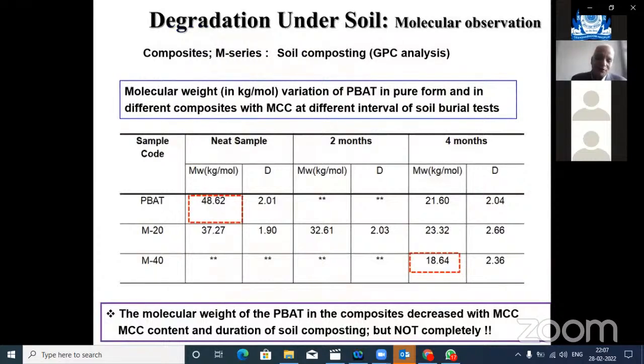So after the samples were degraded inside the soil, they were taken out, they were dissolved suitably in the solvent, and they were subjected to gel permeation chromatography to find out if there is degradation, if there is a deterioration in the molecular weight of the samples. So you can see this is the polymer sample, neat one. It was the weight average molecular weight. So this is about 50K.